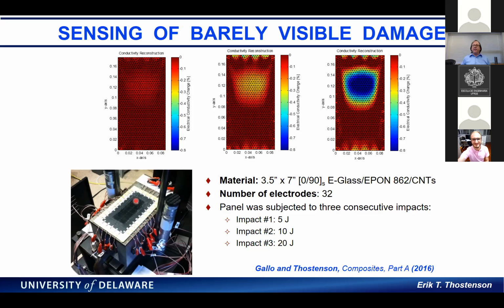And then we did progressive impact. We impacted it at 5 joules, and then 10 joules, and then 20 joules. After each impact, we did the reconstruction. And I think clearly what you see is that location